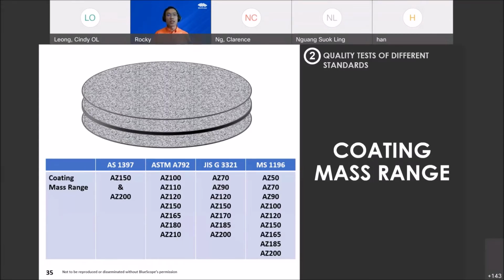What you can see from this table is that different national standards have a list, or so-called range, of coating mass. And you can see that Malaysian standards tend to have the widest range, and it also includes the lowest coating classes, which are AZ50, AZ70, and so on, right?